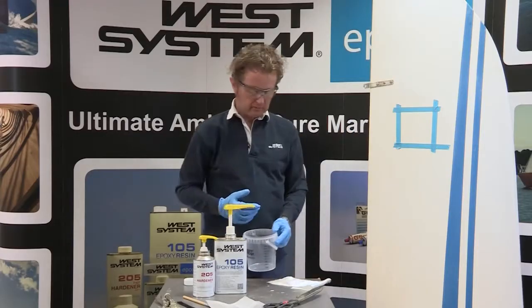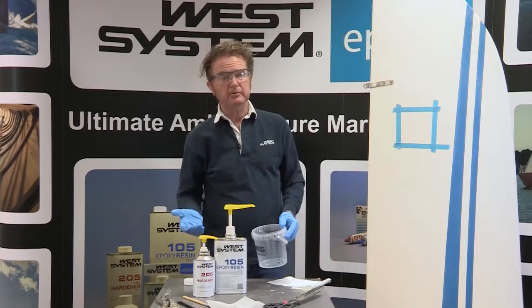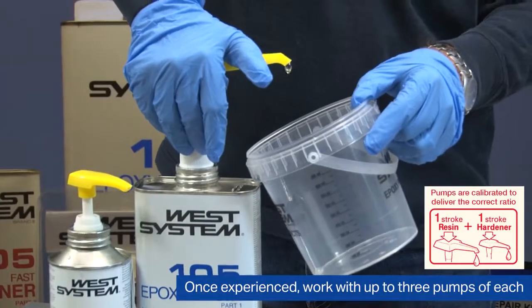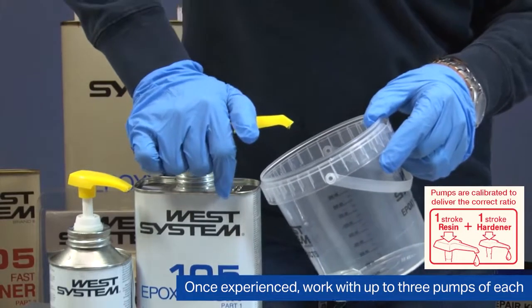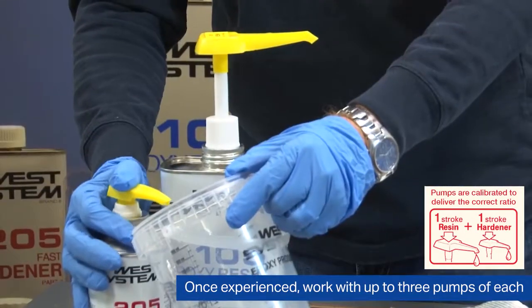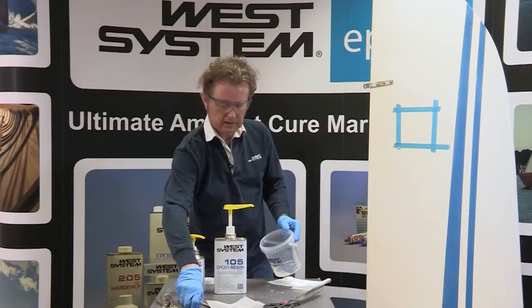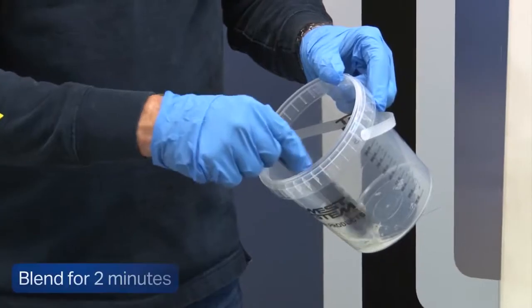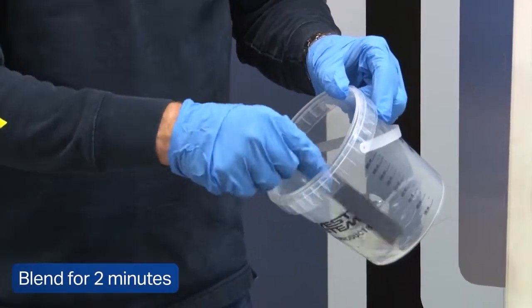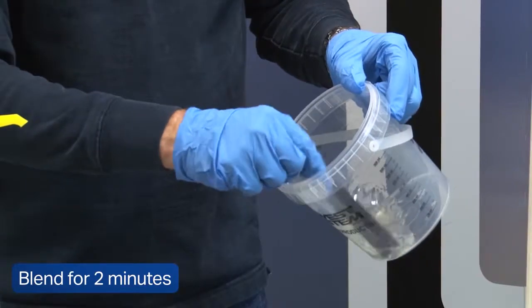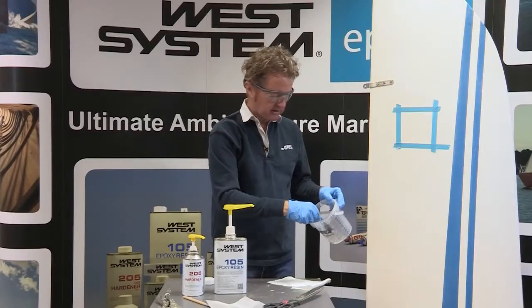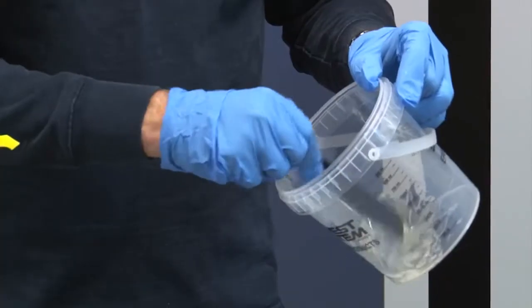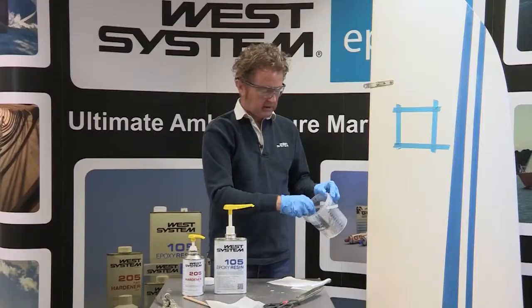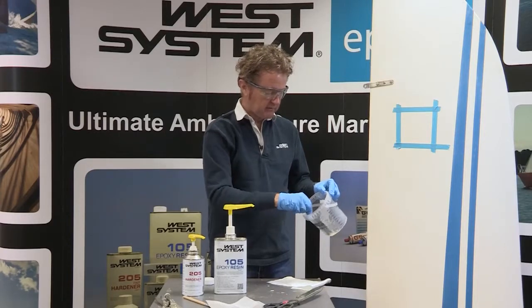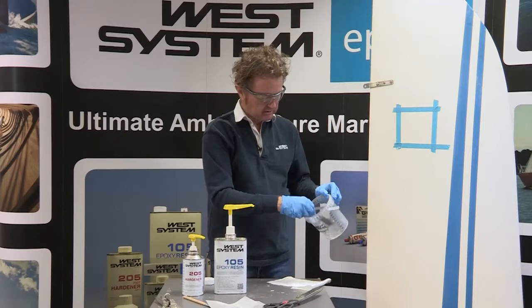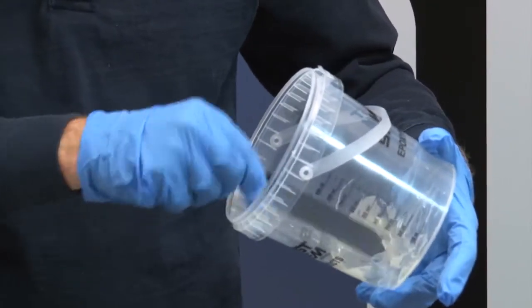Now to do this patch that I'm going to make, I only need one pump of resin and one pump of hardener. So I make sure that I depress a full stroke of the resin and a full stroke of the hardener, and that will give me exactly the correct ratio to mix thoroughly. Now I always suggest that people mix for 2 minutes, so you can count to 120 whilst you're mixing. If you mix this at the correct ratio and you mix it sufficiently, it will cure in a very, very wide variety of conditions. That's blended nicely together.